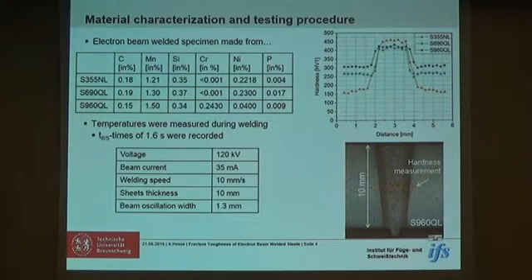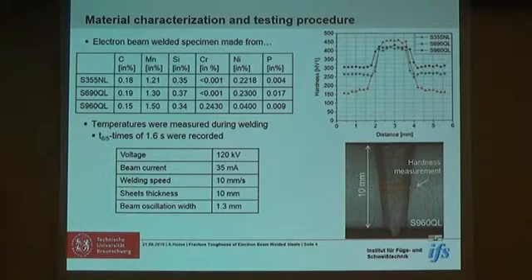For our research, we used 3 different steel grades. The lowest yield strength was around 355 megapascal, going up to 960 megapascal. They were electron beam welded with a voltage of 120 kilovolts, a beam current of 35 milliampere, and a welding speed of 10 millimeters per second, which is rather fast if you compare it, for example, to arc-welded specimens. The sheet thickness was chosen to be 10 millimeters, and we recorded temperatures during welding, and the t8/5 time, the cooling time from 800 degrees to 500 degrees, could be determined to be 1.6 seconds.